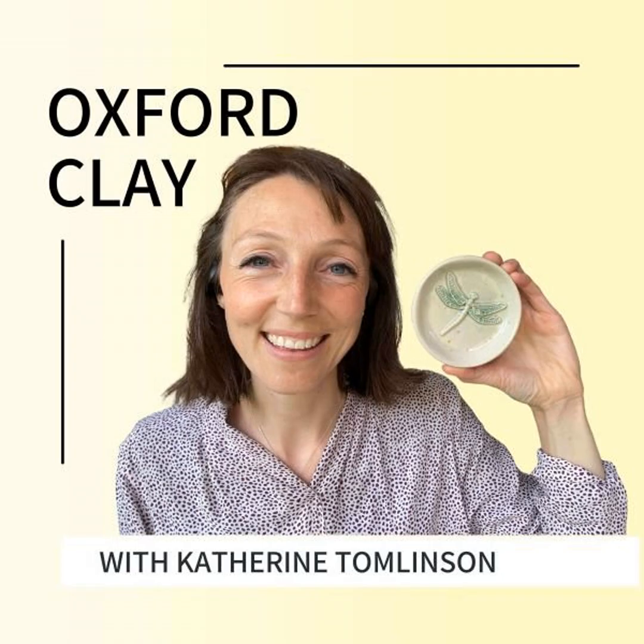So how I make my clay is I measure out china clay, quartz, FFF feldspar, and three different types of ball clay, high mod, high plas, and blue ball clay, with water, and I add a sodium silicate to make it into a casting slip. I also add some bamboo kitchen roll to make it a very strong clay, and I mix all of that together. I can use that for casting slip, but I can also reclaim it back into clay that I can use on the wheel or for hand building stuff.